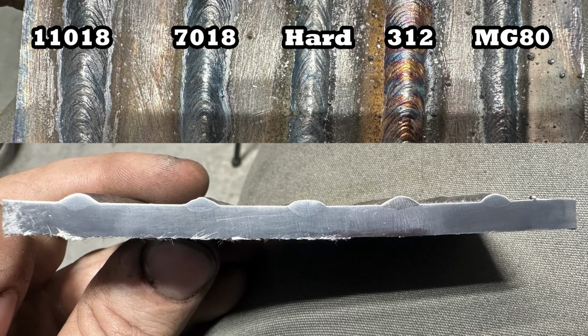The amperage that I was running it at was probably a bit too high, and that you don't want because the bead will tend to dilute too much into the base material and crack. And speaking of cracking, more on that in the next section.